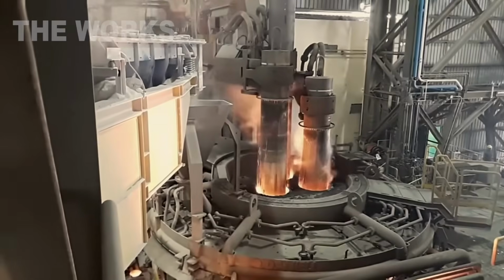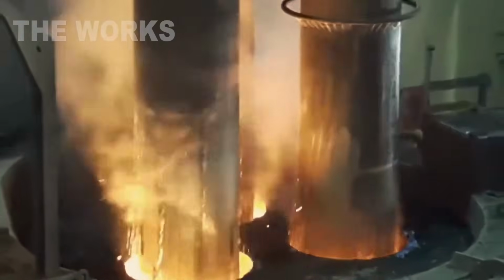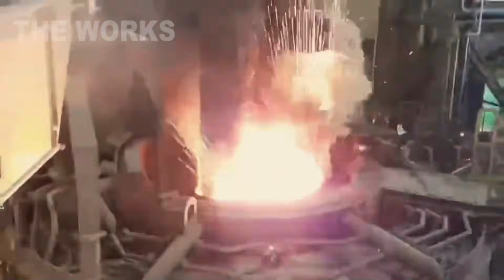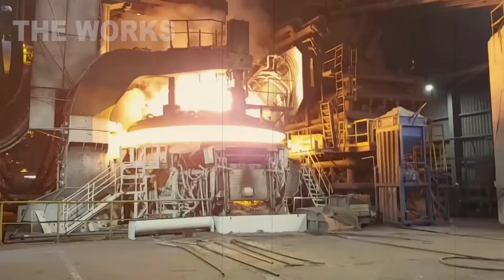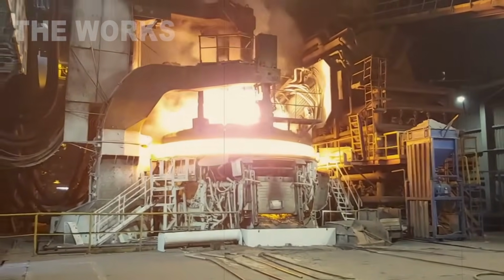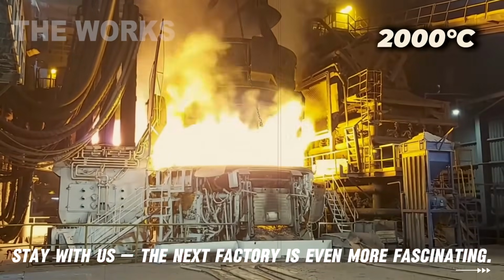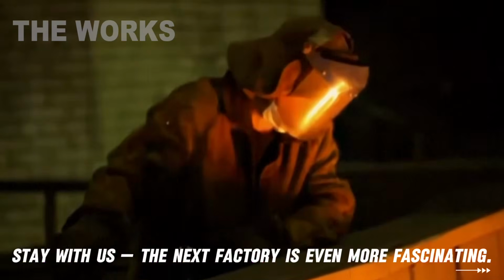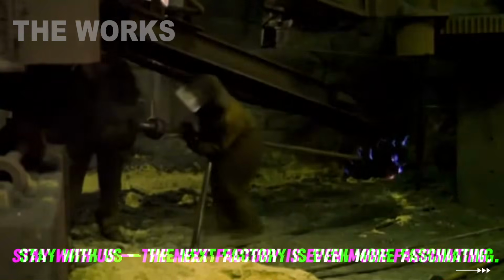When tens of thousands of amps surge through them, an electric arc forms between the electrodes, a miniature lightning bolt that hits temperatures of 3,600 degrees Fahrenheit. That's hotter than volcanic lava, hotter than the surface of some stars. Into the furnace goes quartz sand mixed with carbon, wood chips, coal, or petroleum coke. Carbothermic reduction begins, a chemical reaction where carbon rips oxygen away from silicon dioxide.